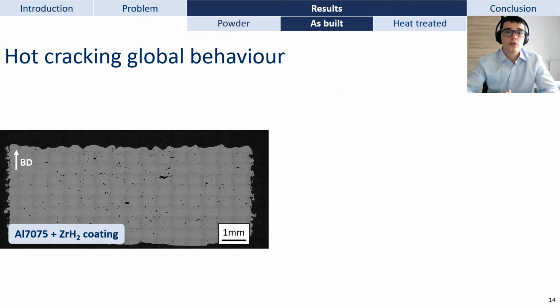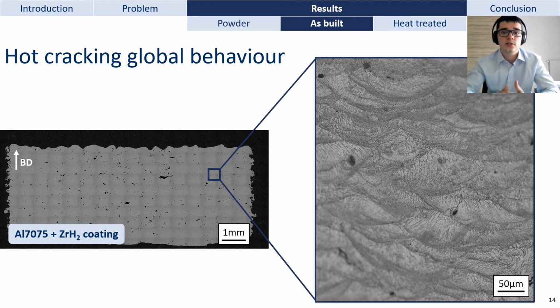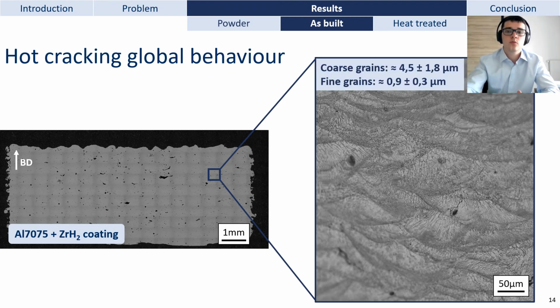For the coated powder now, there is also a total suppression of hot cracking. The microstructure is quite similar to the high content one with the same bimodal structure and grain size, but with a bit less relative portion of the microstructure occupied by the fine equiaxed grains. It is a really encouraging result because it seems that the suppression of hot cracking can be obtained with less zirconium than for the high content zirconium powder mix. However, we cannot compare the coating directly with the low content powder mix since the coating composition still needs to be precisely determined.